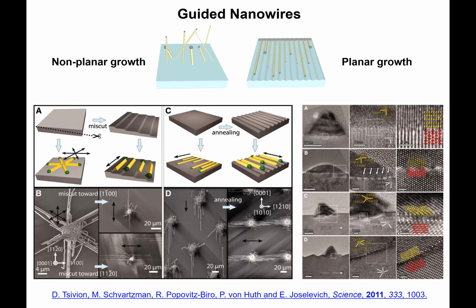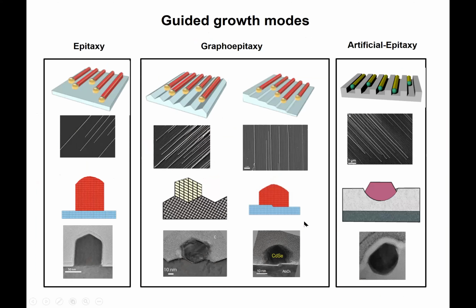So there are basically three main mechanisms of guided growth: epitaxy, graphoepitaxy, which I mentioned, and also an artificial epitaxy that we developed recently, where we can grow guided nanowires on completely amorphous substrates by creating guides using lithographic methods. They also follow these guides when there is absolutely no atomic registry.